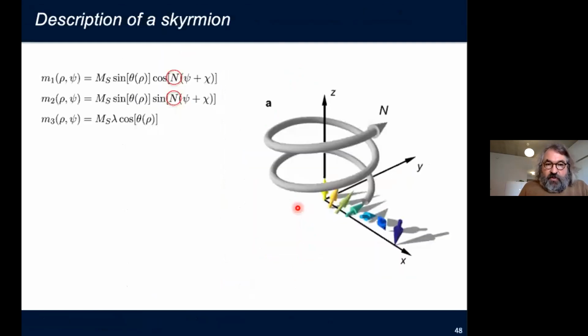The other thing, just briefly to finish that, is what we can measure is the so-called winding number N. The winding number is also encoded in the magnetization components of the skyrmion, and it really describes how often you can map the skyrmion structure onto the sphere in order parameter space to catch all the moments in the skyrmion.